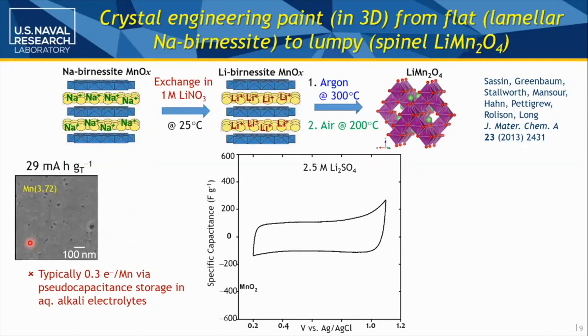But there's other fun things you can do with this lamellar birnessite-like material. So we've got sodium between our layers and water, of course. We're not showing the water. That gives us a certain milliamp hours per gram. Now I'm dividing by the total weight of the electrode. That's another point that makes us growl at our laboratory, because most people won't tell you what they're normalizing to. We always tell you what we normalize to. And in that sort of yellow font, this is telling you the oxidation state of the manganese. So it's not all 4+. And typically this painting in the high surface area on a carbon surface across the literature is giving you roughly 0.3 electrons per manganese center, which is, you know, pathetic.